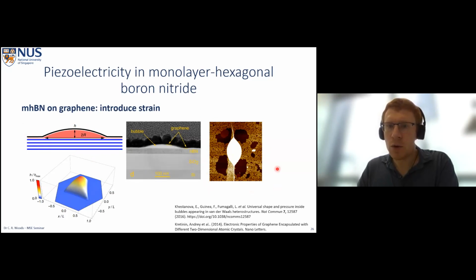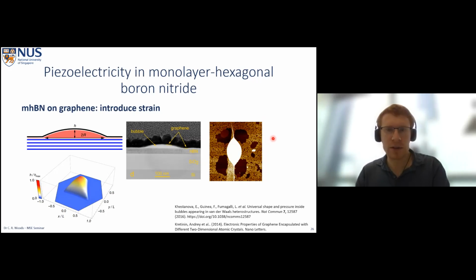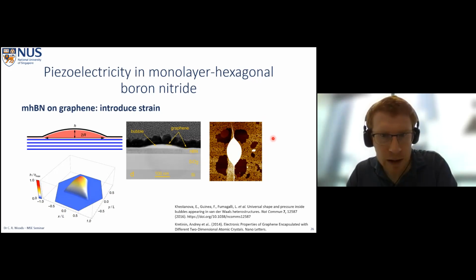And what we saw when we put monolayer boron nitride on graphene is this on the left. So you're looking at an atomic force microscopy image, and this is just some contamination, some incidental contamination. But around the bubble, we see this very strange, almost quadrupole-like looking structures where the contamination doesn't exist in some areas, but does in others. And this clued us on to the fact that we probably have some kind of effect here around the bubbles.